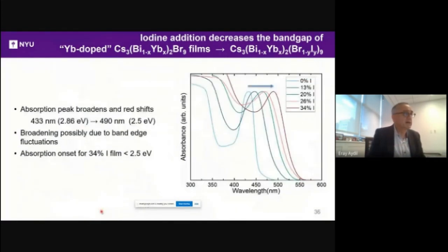The X-ray diffraction peaks shift to lower 2 theta angles, and that's consistent with iodine substitution for bromine and increasing the lattice parameters because iodine is a larger ion. I try to show it by putting a slanted dashed line here. It's a very small shift, but it's detectable. And the trigonal structure is retained. All the peaks are where you would expect. There are some intensity changes in the distribution, and that's because we're changing the texturing a little bit. So there's no sign of phase separation into films that are iodide and bromide, but there is good mixing of bromine and iodine.